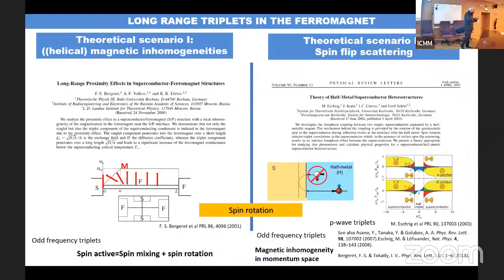But on the other hand, the length scale over which this conversion occurs is relatively long, right? Then, a few years after, Matthias Eschrig, Juan Carlos Cuevas, and Gerd Schön saw that also in strong ferromagnets, even half metals, this conversion into equal spin triplets can occur, right? Now it occurs at much shorter length scales, right? And for a half metal, this length scale can be as short as an atomic distance, right?